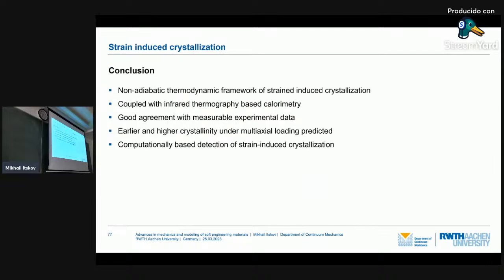Right. Short summary of these results. We presented here a non-adiabatic thermodynamic framework of strain-induced crystallization. The model was coupled with infrared thermography in order to measure the heat source. We obtained rather good agreement with experimental data, and we observed that under multi-axial loading, for example, by biaxial loading, the crystallization appears earlier and with a higher intensity.